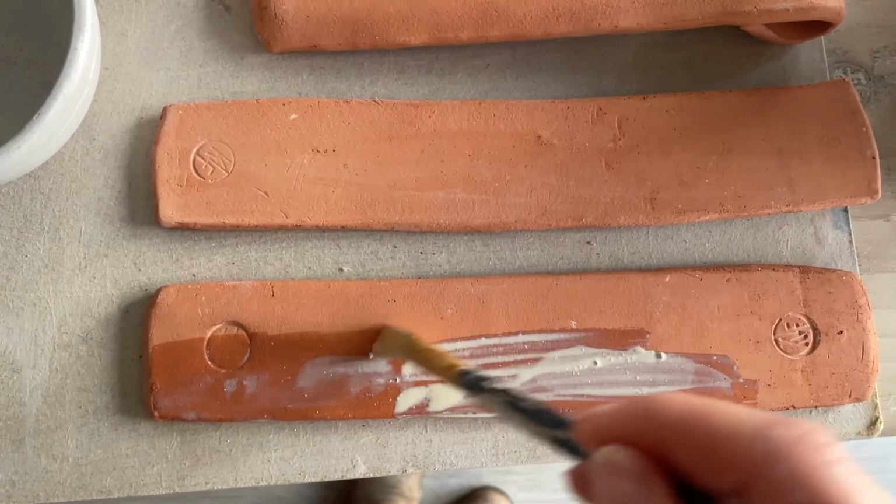My final design, I'm going to use a brush on glaze I had hanging around my studio. This one is called Turquoise Granite and it's from Botz. I used 3 thick coats and allowed each one to dry in between. I gave my incense holders time to dry out overnight before I packed my kiln and fired it to 1220 degrees centigrade, cone 6. That is 2228 degrees Fahrenheit.